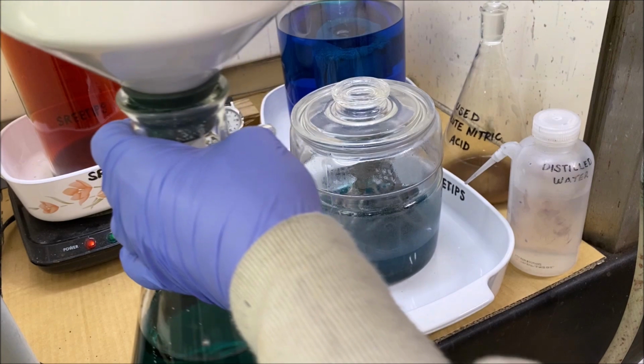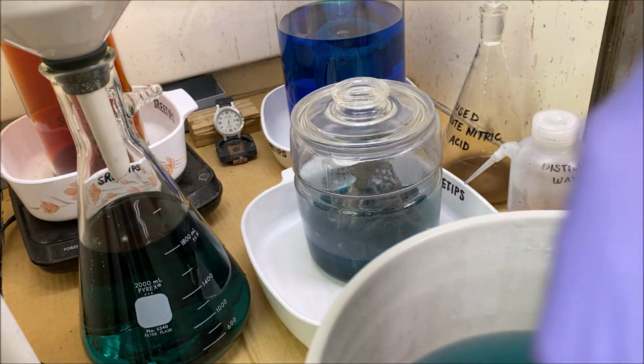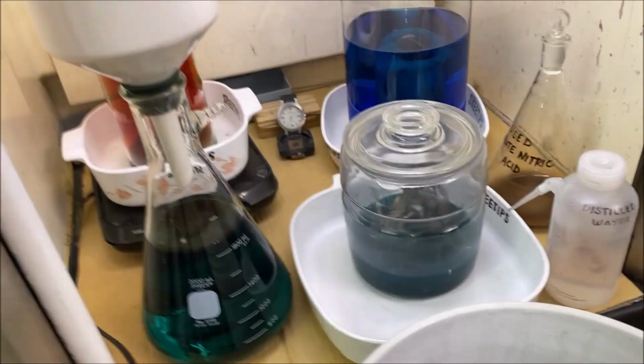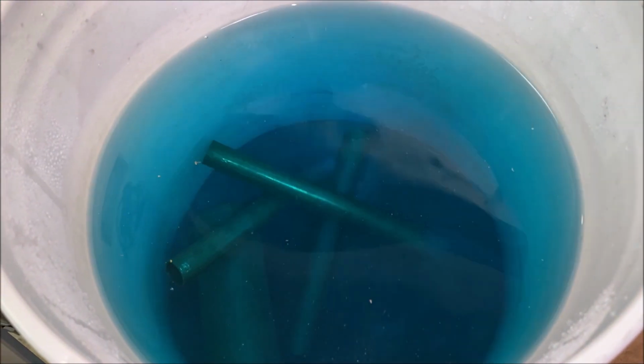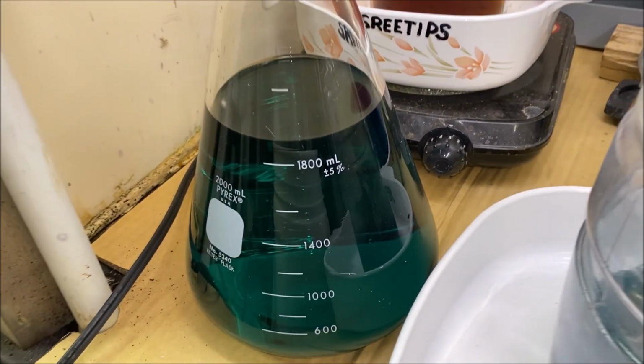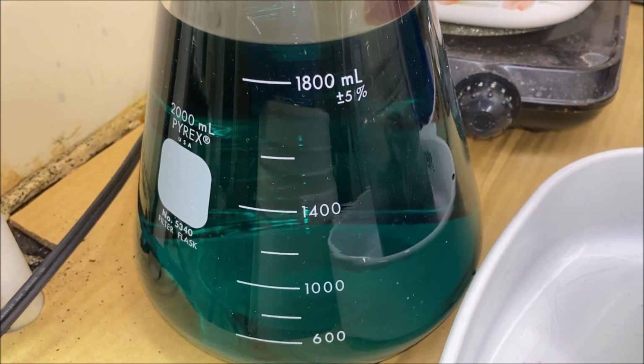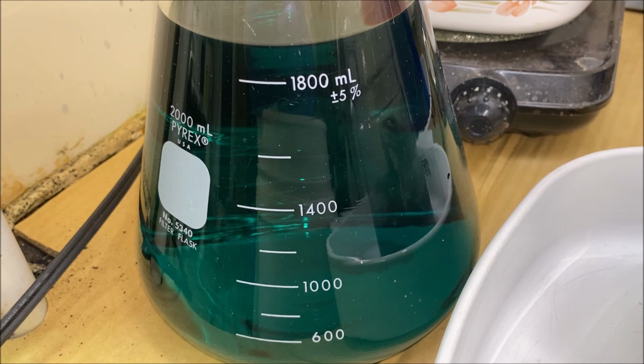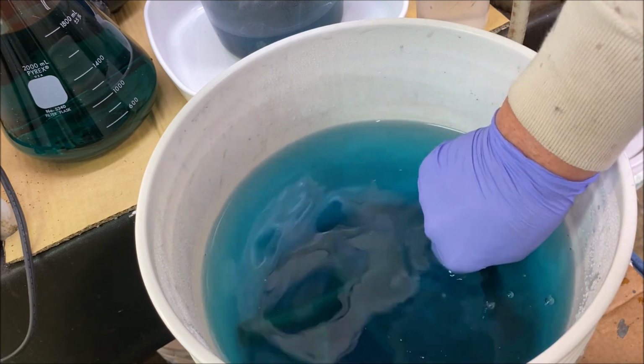Flask up here out of the way. I've got my silver bucket down here. And this is the bucket that contains my cement silver. If you remember, when we harvested the silver out of silver cell number one, I added the rinse water to this bucket, and I've added some pieces of clean copper down in there. And what I'm going to do now is pour this solution that's got a ton of silver in it into this bucket, and we're going to recover the silver out of this solution. It will cement out on these pieces of copper down in this bucket. If you look down in the bottom of this bucket, it's full of cement silver.